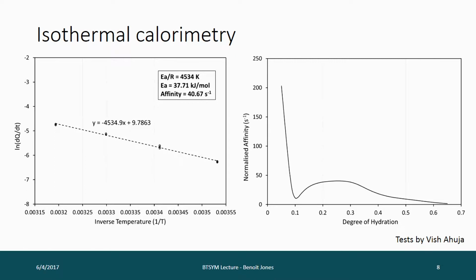And on the right, you've got the normalized affinity, which is a function of degree of hydration. So the big spike at the beginning is, in this case, the accelerator reaction. If the normalized affinity is very high, then that means it's really easy for chemical reactions to occur. It's kind of like the potential difference or voltage of chemical reactions, as an analogy. So the higher it is, the easier it is for reactions to occur. So you have this accelerator reaction, and then even with an accelerated concrete, you still have a bit of a dormant period, and then you've got this long, lower peak, which is the main silicate reaction of the cement. And that's where most of the strength is happening.